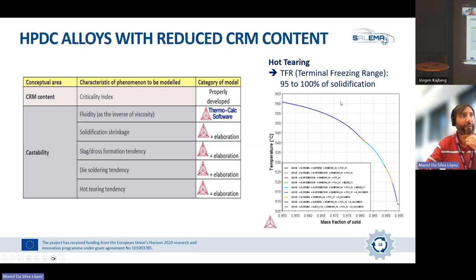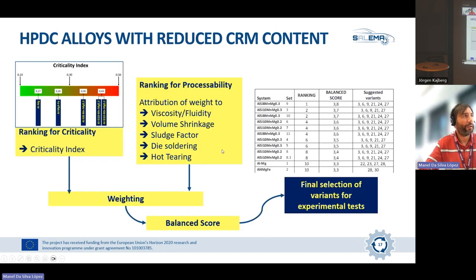As an example, to determine the tendency of hot tearing, we define from the solidification curve the temperature gap between 95 and 100% of solidification. That gives us an idea of how the hot tearing of this alloy will be. With all this data, for over 150 alloys in total, about 70 for high pressure die casting, we calculate the criticality index, taking into account the amount of magnesium and silicon present in the different alloys, mainly, which are the two critical elements most commonly present in aluminum alloys.